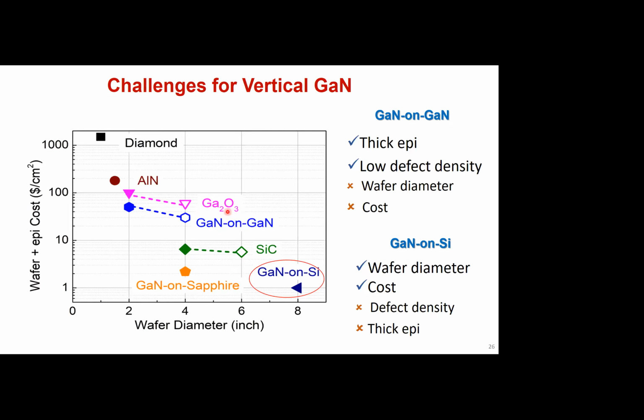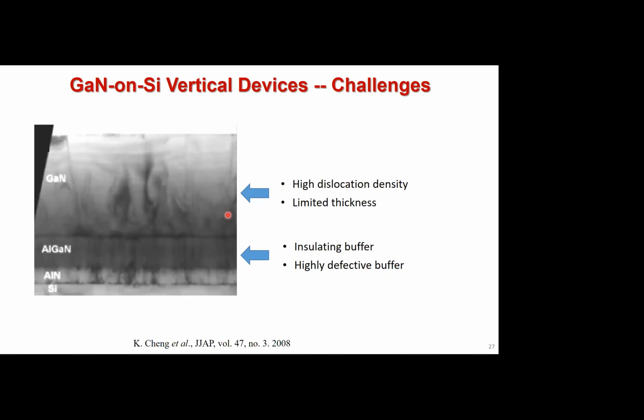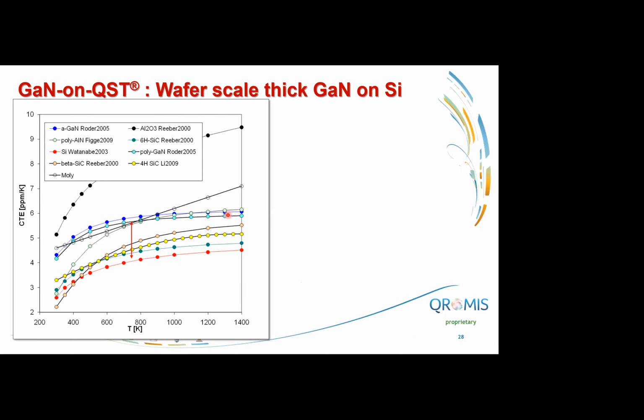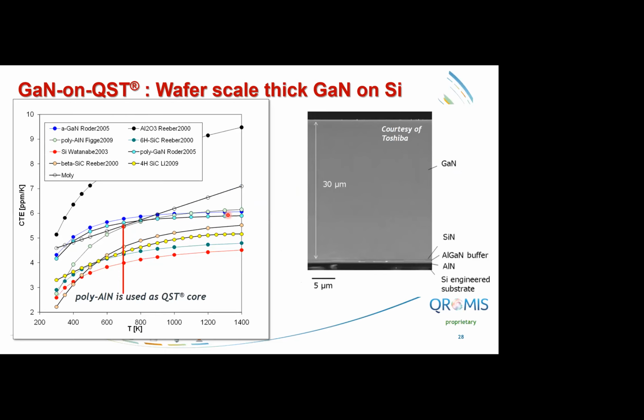So you can see if you look at the state of the art gallium nitride on silicon. Just one comment from your presentation. The Toshiba, they did grow 30 micron on silicon. They use silicon nitride treatment and they did something. Using these techniques, they can manage to grow 30 micron crack free, it seems. Yeah. So in that case, gallium nitride on silicon should get the market, isn't it?